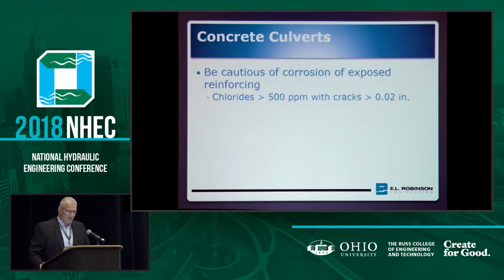Okay. One thing to be cautious of, even if you have not so low of a pH and the things that are kind of damaging the concrete, you have to be worried when you have high chlorides and you have cracks greater than about 2/100 of an inch. So at this particular point, this is when the reinforcing, in general, again, everything I'm talking about is general. I don't want to say this is the hard, fast number because it's not that simple. These are complex processes that are very difficult to repeat when you go from one state to another state to another state. Particularly now, I'm talking about concrete, but particularly with metal. With metal, state to state to state, the results vary a lot. Now, concrete and aluminum, if you go anywhere in the country, you'll get pretty close to the same range of acceptable values. But metal has a really, really high variability.